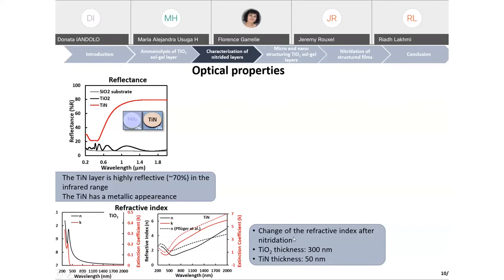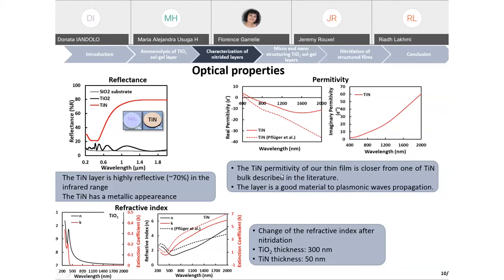From the permittivity of the titanium nitride in our film, the permittivity is close to that of the titanium nitride bulk described in the literature. This little difference is also attributed to the porosity of the layer. We also see that the layer is a good material for plasmonic wave propagation.